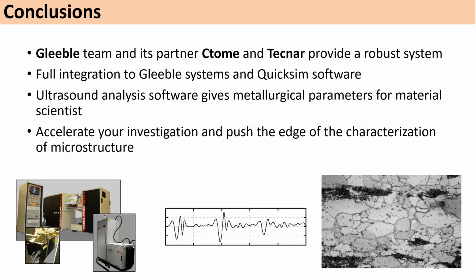The question here says, laser shots generate both longitudinal and shear waves. Can the Lumet sensor pick up shear wave signals or particle vibration parallel to the surface? Yeah, that's again a great question. So in the conventional configuration of the Lumet, it is set up to generate mostly longitudinal waves. It can be changed simply by increasing the size of the generation spot slightly to enhance the formation of shear waves initially. But shear waves will always be generated inside the sample as this longitudinal pulse propagates through the sample, by what we call mode conversion. So shear waves will always be present.